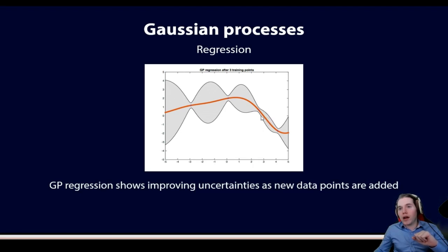But if you're trying to find the minimal value, for instance, the minimal hardness, then you might say that this area, even despite it being so uncertain, is actually not that interesting, because even given the uncertainty, you'll never get as low as this point. But if we look here, the uncertainty is so large that the point might still be lower. So you can use this to abandon parts of your material space before you've even properly explored it.